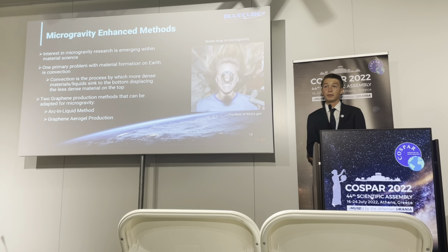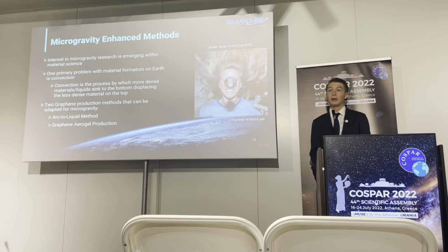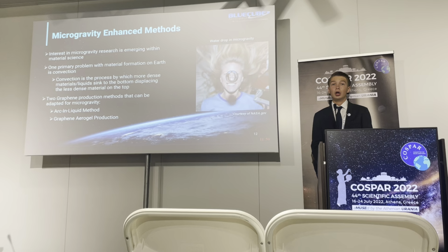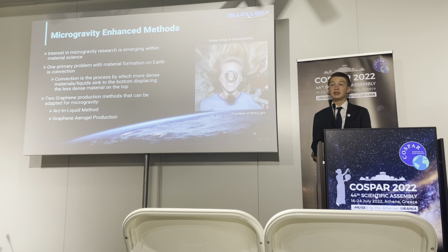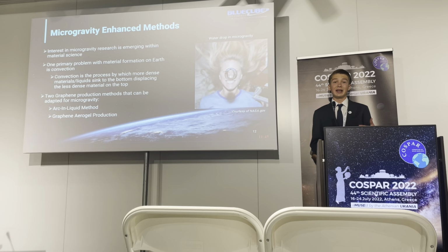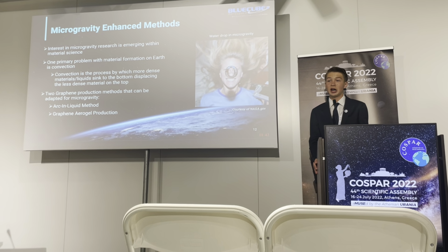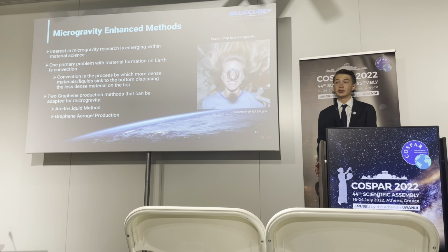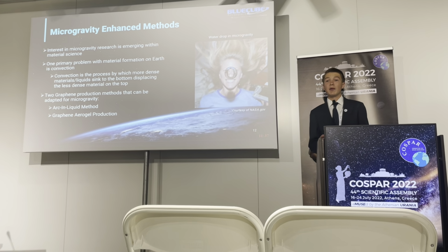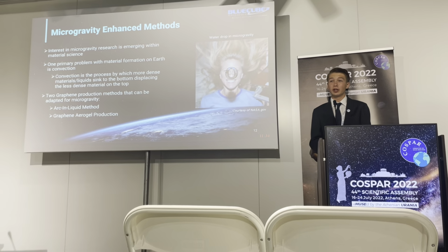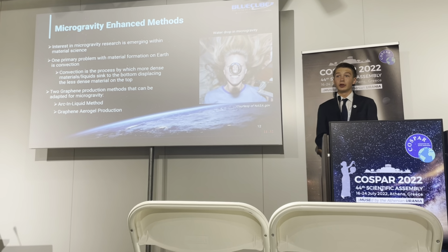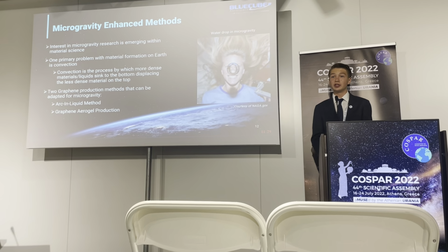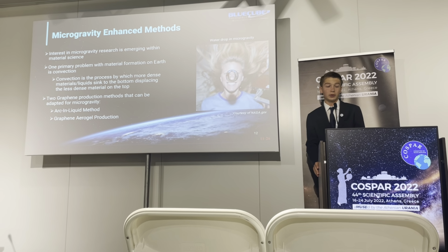Specifically, one of the main problems with forming materials on Earth is convection. Essentially, convection is the process by which liquids in an experiment move based off of the forces of gravity, with more dense materials sinking to the bottom and displacing the less dense liquids and materials on top, which generally creates less pure and worse performing materials. However, in microgravity, there are much fewer forces acting on the liquids in the experiment and the materials, which generally leads to the creation of more pure and better performing materials.